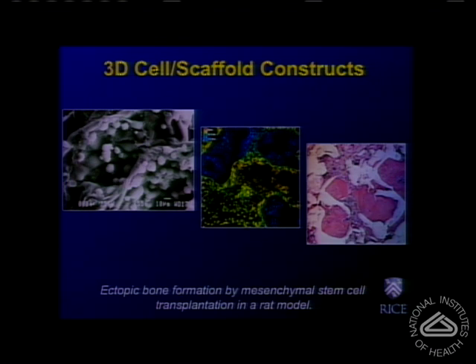So using imaging techniques such as confocal microscopy, one can image the growth and migration of cells within the three-dimensional structure. The color is indicative of the position of the cells in three dimensions, with yellow being very close to the surface and blue deep inside the pores of the scaffold. And when one takes these three-dimensional cell scaffold constructs and implants them in orthotopic or ectopic sites, one witnesses the formation of a new tissue, as it is in this case the formation of a bone-like structure following the implantation of these constructs in the mesentery of a rat model.